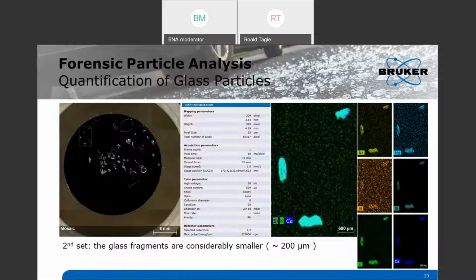So basically now we just did more or less the same. The first ones were relatively large particles in the millimeter, sub-millimeter range. Now what happens when my particles become smaller? Here we would like to discuss a little bit what happens with acquisition time and small particles, and how these might influence my identification. And you see the measurement time here. The scan was done, the overall time was 25 minutes.